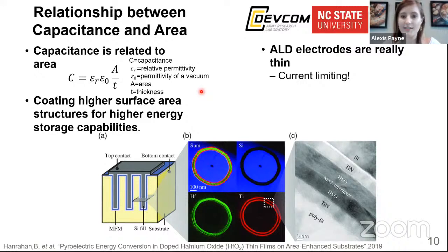You can see trench capacitors in commercial products. That means you're coating a higher surface area under the electrode for the same footprint, yielding a higher capacitance for the same footprint. And this has been done with hafnia thin films, as you can see in this panel. However, when you're thinking about actually using these, let's say for a pulse power application, you come into a problem,